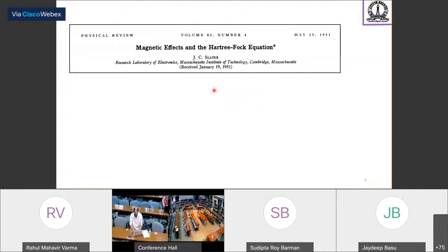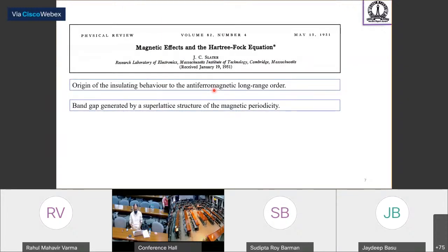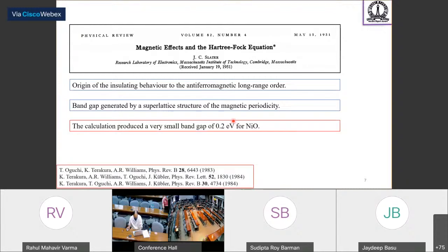On the other hand, Slater ascribed this insulating behavior to magnetic ordering, such as antiferromagnetic long range ordering, because most of the Mott insulators have magnetic ordering, at least at low temperature. So this insulating behavior comes about because the band gap is generated due to the doubling of the unit cell due to magnetic periodicity. Indeed, some of the calculations produced a very small band gap of 0.2 electron volt for nickel oxide. But this Slater insulator is different from the Mott insulator, where the insulating gap arises due to the Coulomb interaction energy U.